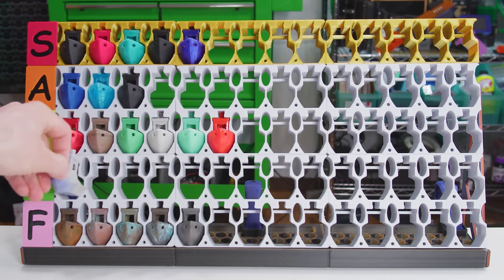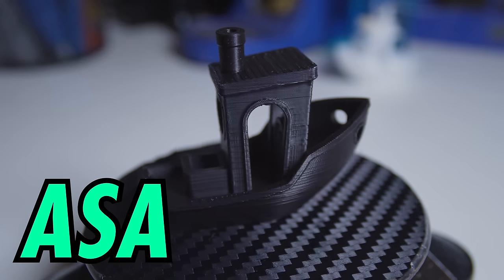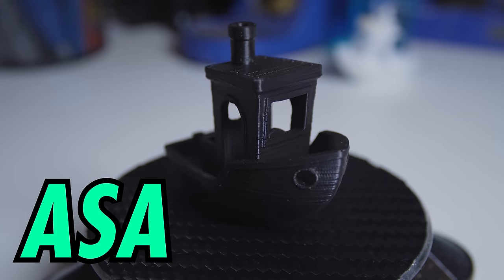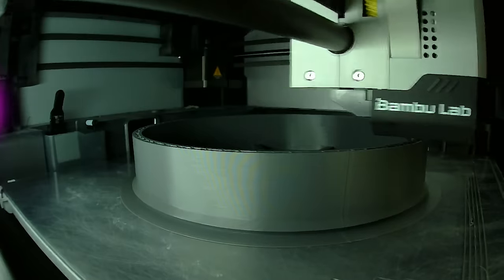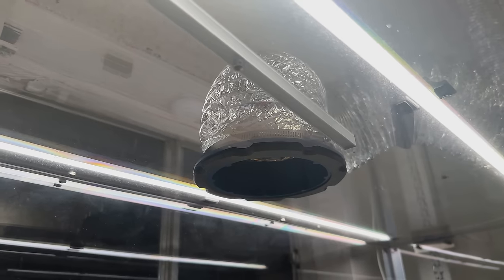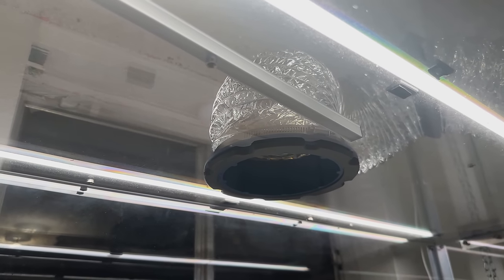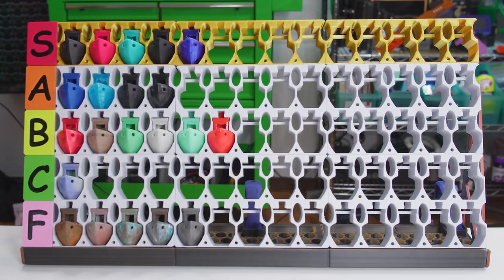Acrylonitrile Styrene Acrylate is a chemical cousin of ABS, but its upsides are upper, and its caveats just less concave. ASA withstands heat all the way to the boiling point, and can survive indefinitely in direct sunlight. It's also just as tough as ABS, and has a really handsome matte surface. Molten ASA is also one of the least viscous of all the polymers, so if you're trying to set speedboat records, this is the filament of champions. It's not easy to print per se, but it does warp a lot less. It still off-gases just as much filthy effluvia, so wear a snorkel. It's a bit of a bitch to print, but if your project needs to take a beating, it's a really good choice. I'll put ASA in A tier.